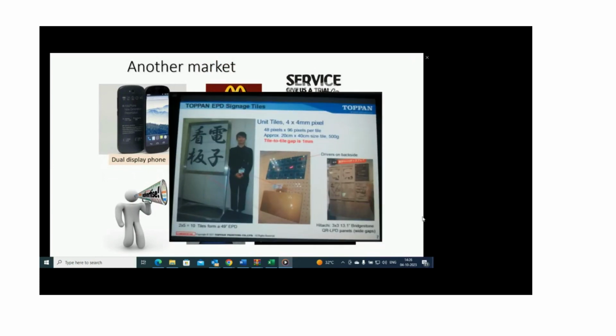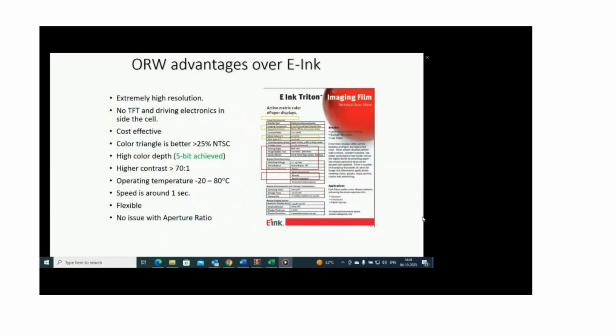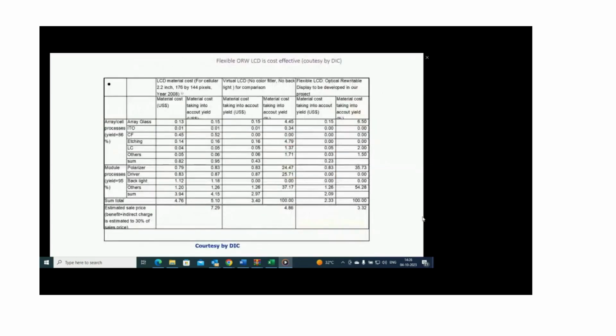In comparison with electronic ink, which is usually used for the purpose, for instance, by Toppan company in Japan, our e-paper has extremely high resolution, no TFT array, so it is very cost effective. The color triangle is better than 25% NTSC. High contrast ratio, very wide operation temperature range, and the speed at which you can write and erase the image is about 1 second. So it can also be made flexible.